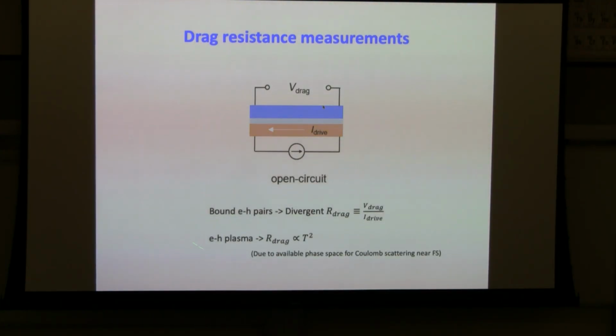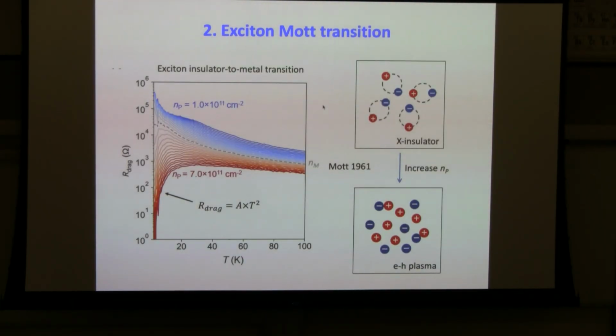On the other hand, if you have an electron-hole plasma, the drag resistance will be proportional to temperature squared, because when you increase the temperature, there is more available phase space for the electrons in the hole Fermi surface for Coulomb scattering near the Fermi surface. Okay, so let's look at the result. This is the drag resistance as a function of temperature. The different curves are different pair densities. At low pair density, which are the blue curves here, you have excitons, and as a result, when you cool down the temperature, the drag resistance just diverges with decreasing temperature.